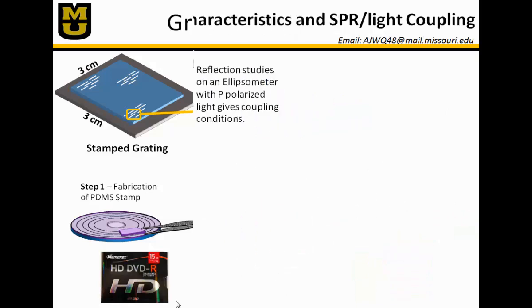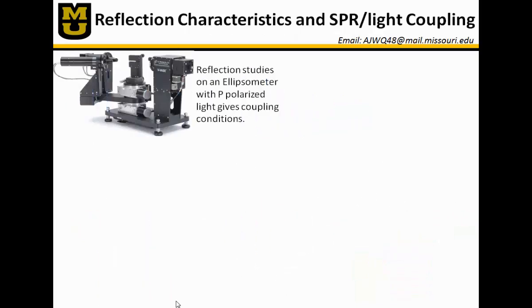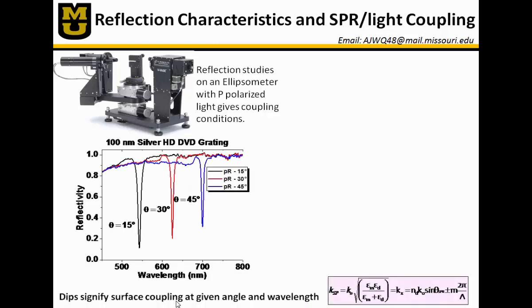So one way that we can measure the SPR, or how much light we can basically get to absorb into your grating, is by taking reflectivity measurements. We typically do this with an ellipsometer using p-polarized light. We scan spectroscopically across several wavelengths and several angles, and in the resulting scan, you'll see these sharp peaks that are indicative of SPR coupling. So at each of these wavelengths and these angles, you generate SPR. And this can also be described theoretically using this equation, which is a little bit rough there, but this left half is the momentum required for generating SPR, and this right side is the momentum of your incident photon plus the diffracted momentum.